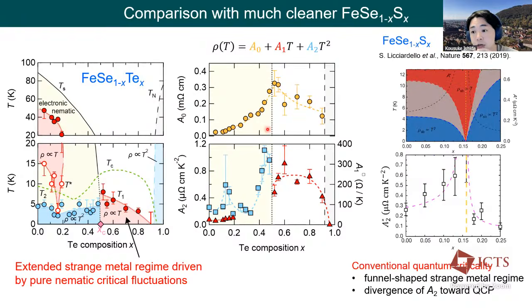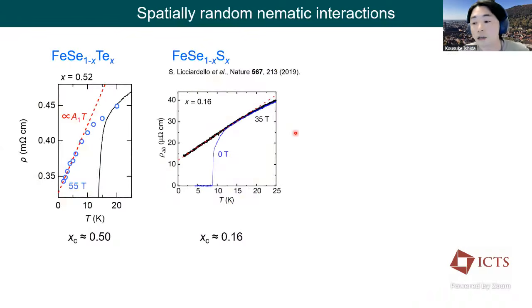But this observation should be compared with iron selenium sulfide, which shows a classic quantum criticality. There are two key features. One of them is the enhancement of the T-square term towards the QCP, and the strange metallicity appears in the funnel-shaped region above the QCP. But in the case of iron selenium telluride, the T-square term is enhanced towards the QCP, but the strange metal regime is observed in an extended broad range rather than a funnel. So obviously, this raises a question on the reason behind this contrasting quantum criticality.